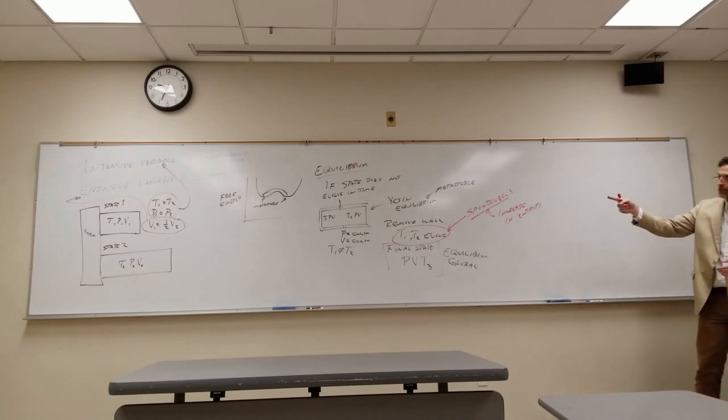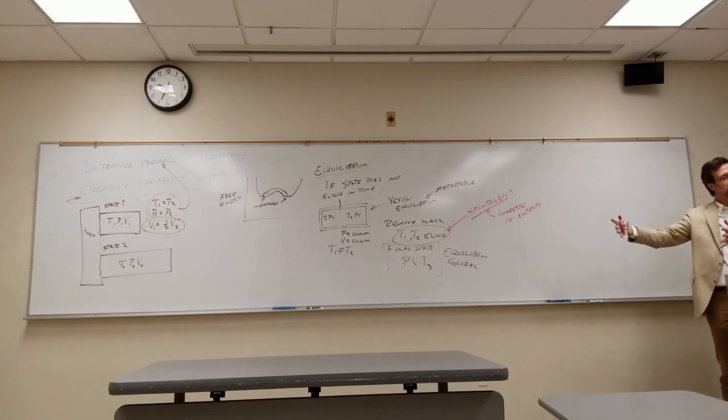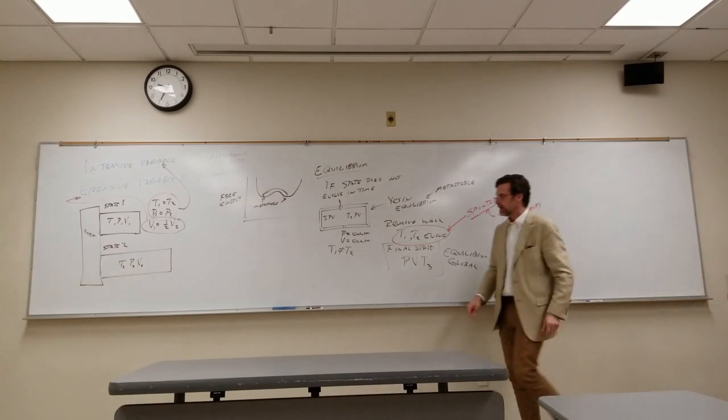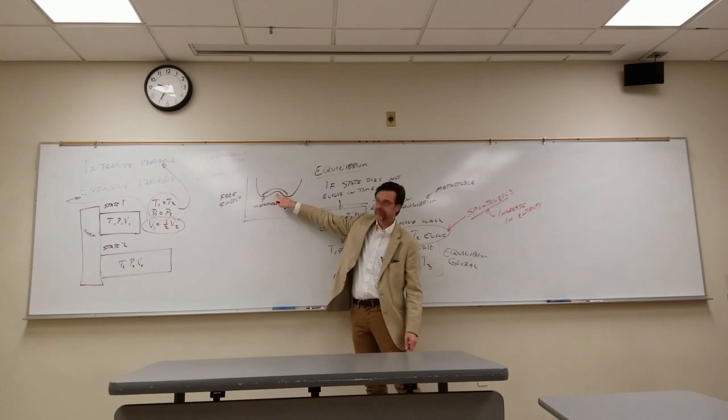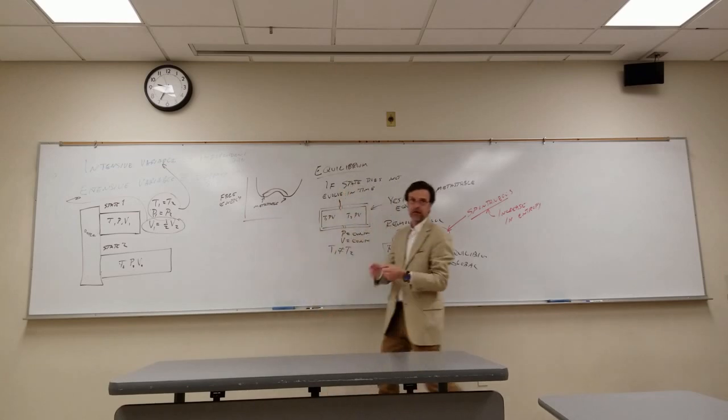In the case of piezoelectric materials, in particular perovskites, which are kind of the workhorse of the piezoelectric world, what we're doing is introducing the old-fashioned ones, single stoichiometric compounds. We weren't actually doing much, we were just taking them off the shelf. The new ones, though, we are changing the composition, and by changing just slightly, 5-6%, we're able to tune what the barrier is, and we're also able to tune how far apart these states are, how large of a change they have.